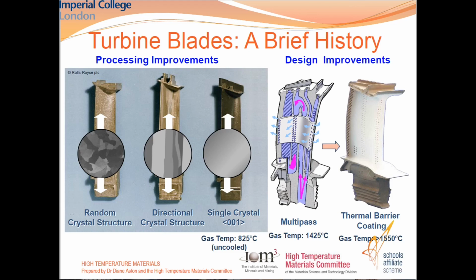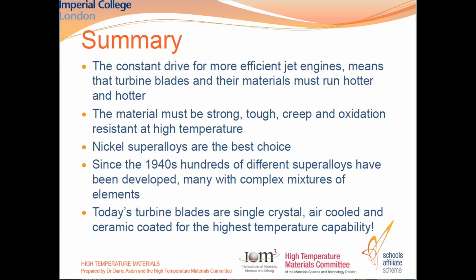So if you have a chocolate teapot, but you cool it from inside, you might expect it to stay solid. It's the same thing here. 1425 was the maximum temperature that was reached from internal cooling with these blades. Now we still needed more than that. So one of the things that is done these days is to coat them with ceramic. So they are cooled internally and they're coated. And that way the alloy can stay strong up to 1600 degrees and work at the selected operating temperature.